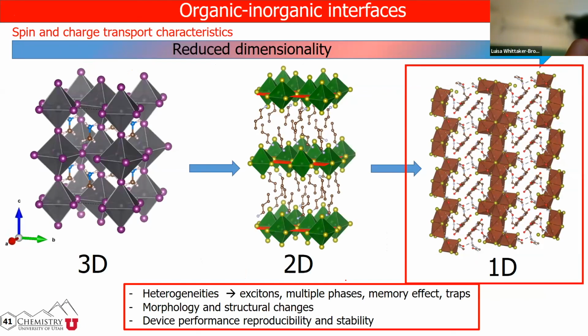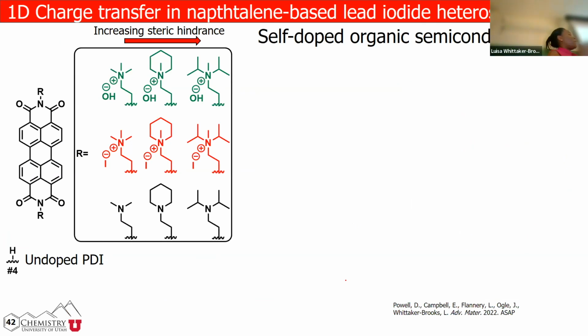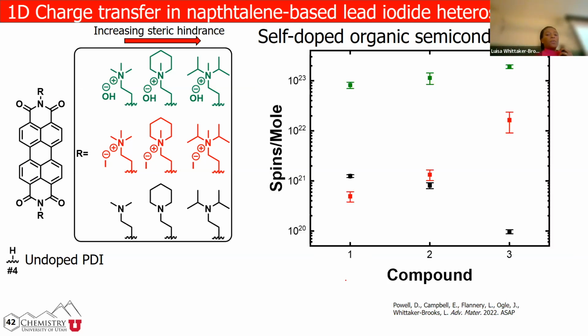That's going to take you like 1 minute, promise, right? My heart is divided in two, so I actually have an organic cap as well. And the thing with organic materials is that they suck, okay? And it's actually nice not to be in Utah because I can say suck too, right? So we try to find ways of creating dopants that will increase the carriers of these materials, okay? We put these dopants in, and then you have an increase in the spin concentration of these materials because you end up forming radicals, and these are half-integer spins, so you can actually map them by doing EPR.